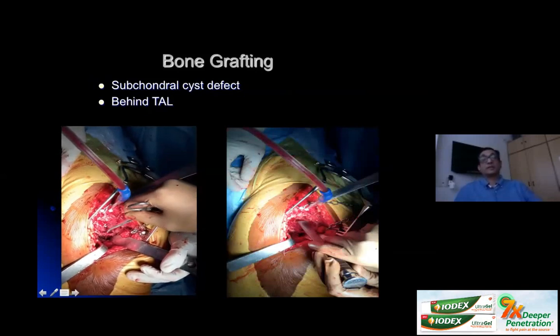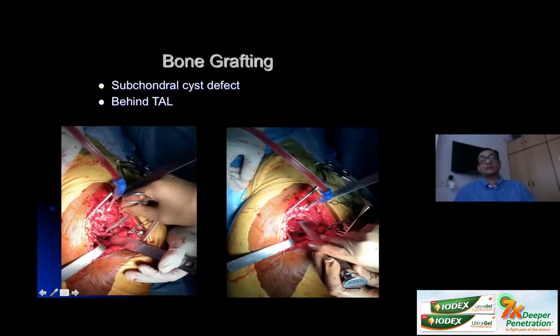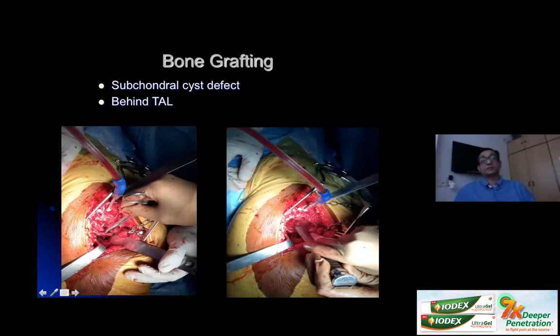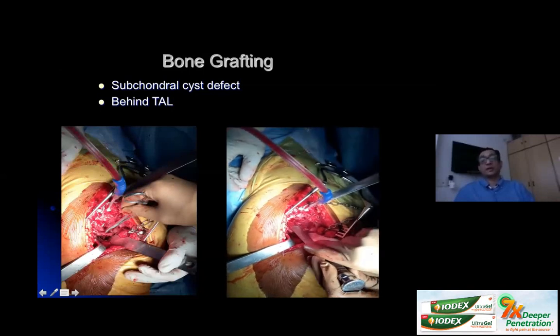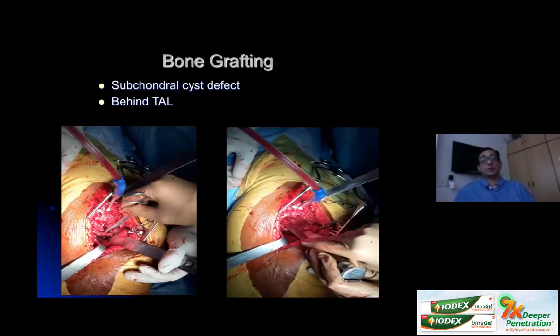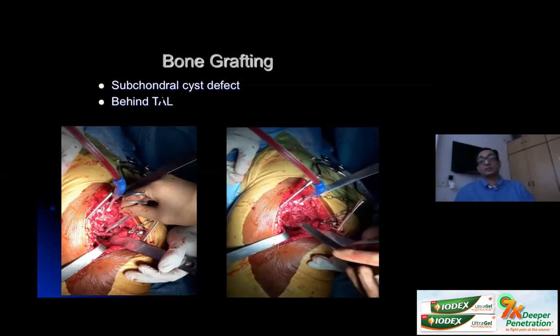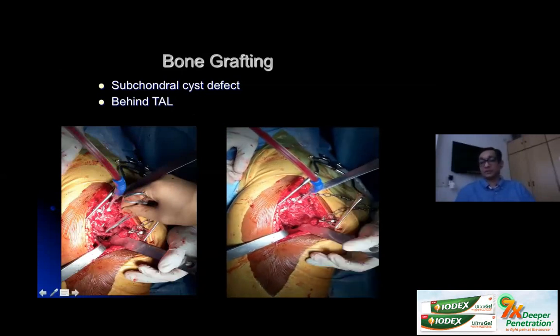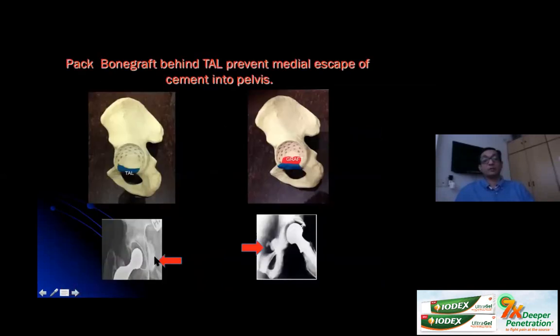Next step would be to graft the cyst. Sometimes you end up seeing an acetabulum which has multiple cysts. There's always a gap behind the cup, which you need to fill up with some bone grafts that you have. Otherwise, what you end up with is an escape of the cement on the medial side, which can damage some critical structure, and also sometimes looks very ugly on X-rays. So always take some bone graft and pack it behind the cup, the way I have shown you here.